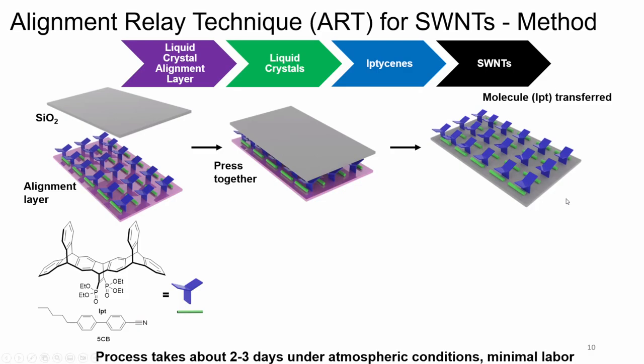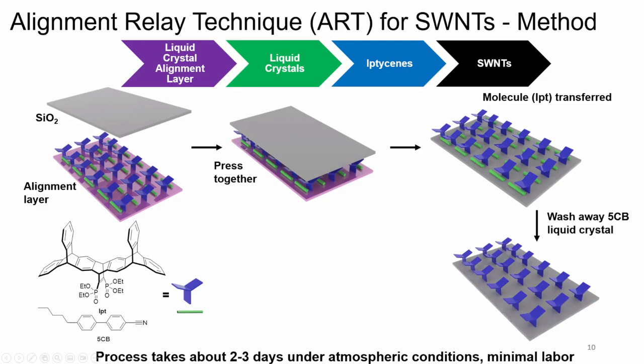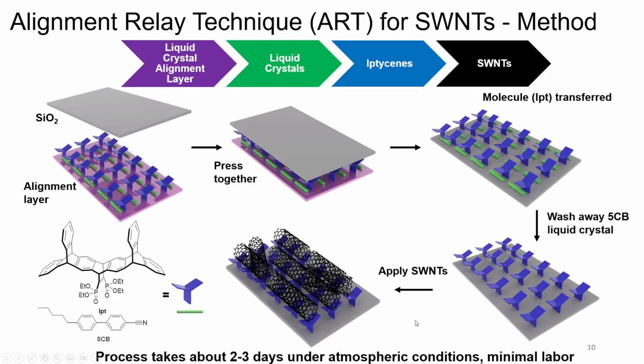What's really nice is that we can wash away all the excess molecules that are not bonded, along with the liquid crystal. The liquid crystal itself is just a solvent. It doesn't bind to the surface at all. We can collect it, concentrate it, and reuse the solution later again, which gives a nice sustainability aspect to the chemistry. Once we have our functionalized substrate with all our aligned molecules, we take the functionalized wafer and place it into a solution of carbon nanotubes. The carbon nanotubes are a homogeneous mixture. We place the wafer in the solution and allow the carbon nanotubes to deposit onto the surface.